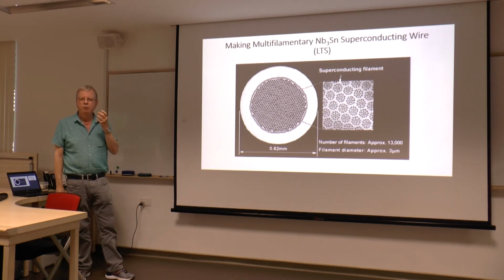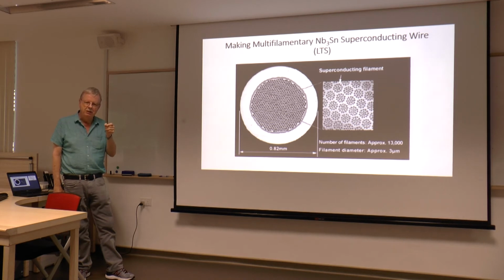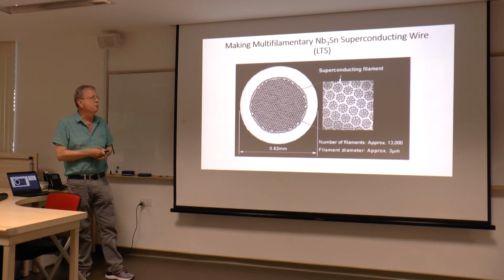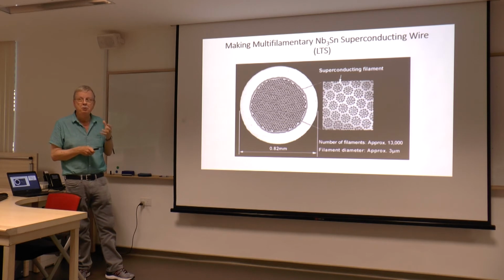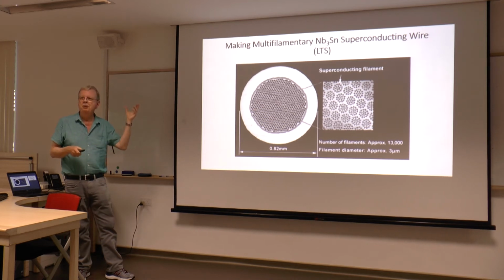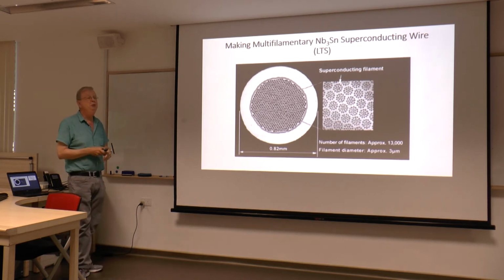You use the copper for thermal sinking of the wire in case you have a local fault where something goes non-superconducting, and there's some joule heating. That heat gets carried away by the copper. So you have the copper present to give you some thermal stability, and normally 3 to 1 is a good ratio. And you might say, well, I'm losing 75% of my current carrying capability per diameter wire because you insist that 3/4 of that wire be copper. Well, yes, but magnets made out of this stuff cost over $100,000, and if you have a failure where the wire breaks in one spot, in a magnet where you have maybe 10 miles of wire in there, the $100,000 magnet is trash, because you can't unwrap the magnet and go find the one spot where the wire melted through. So you need thermal stability, you need the 3/4 copper.